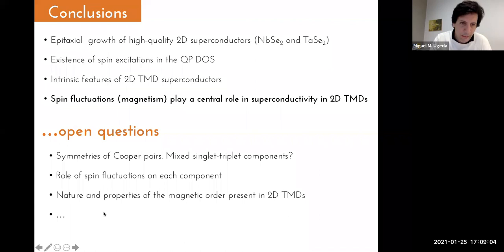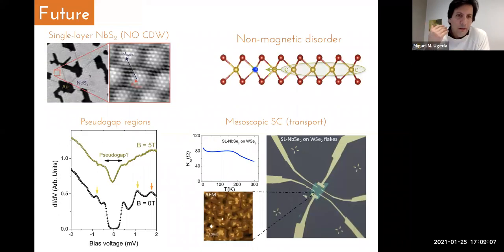And to finish, let me just give you some flavor about the future measurements that we are planning to do. We would like to repeat this experiment in single layers of niobium disulfide, which is a system that in general has no charge density wave. So in principle, we could be able to rule out the Higgs modes because we don't have the charge density wave that could be coupling. We would also like to study the presence of magnetic order in these 2D materials by putting some non-magnetic impurities in the system and see how the scattering behaves in this case.